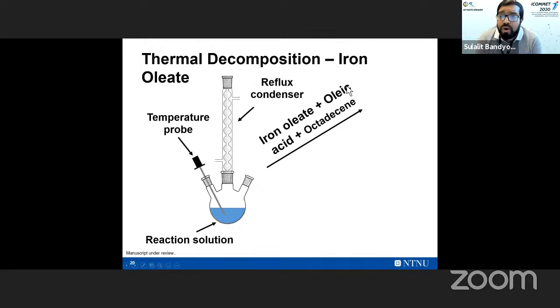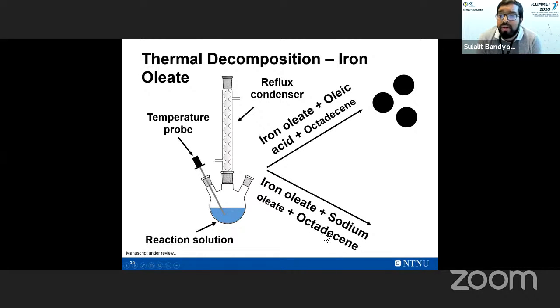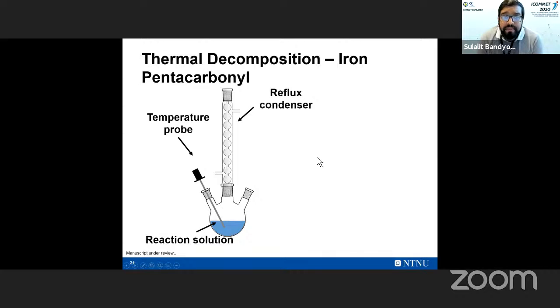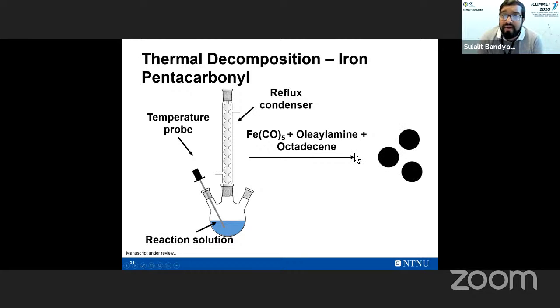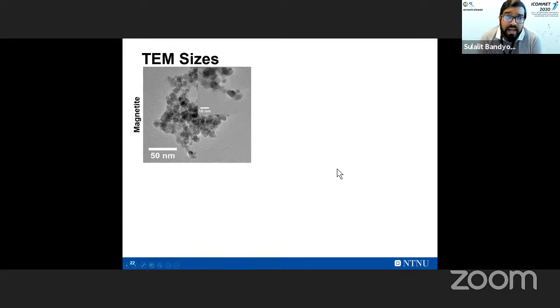Depending upon what you use, whether oleic acid or sodium oleate, we get different shapes. You can vary the shape from spheres to cubes, depending on oleic acid or sodium oleate, which are basically both passivating ligands as well as reducing agents. In another thermal decomposition, we widely use iron pentacarbonyl, which mostly gives us spheres, but here also we can vary the crystallinity of the iron nanoparticles, as I'll show you in the next slides.